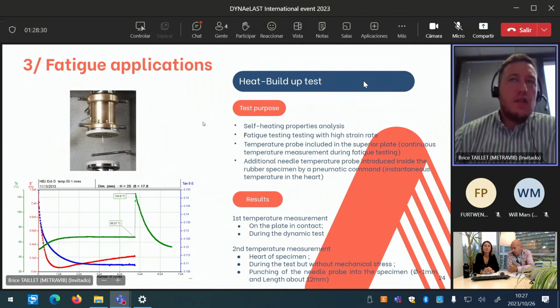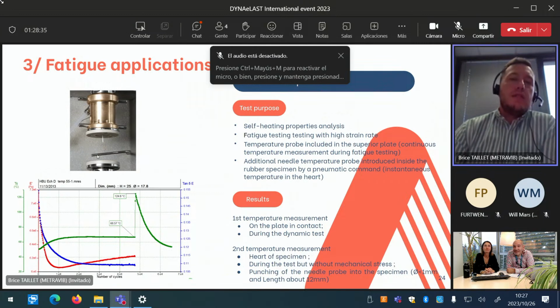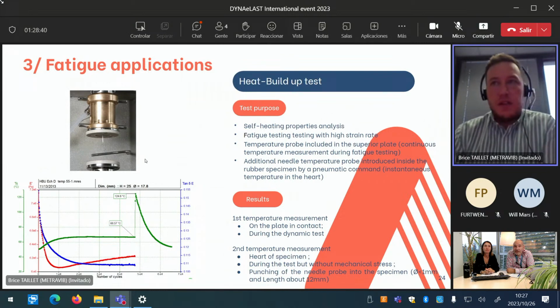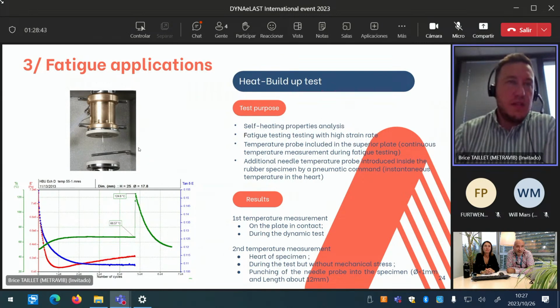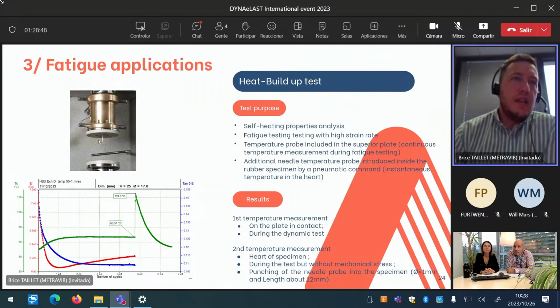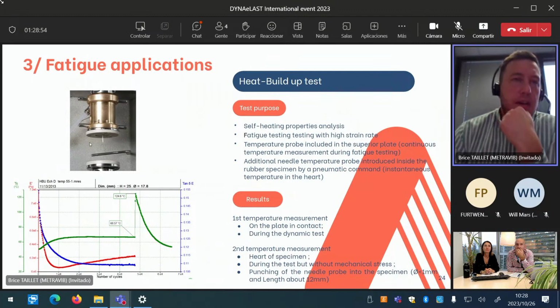Okay, one other interesting test is the heat buildup test. Heat buildup is to characterize the self-heating properties of materials. We use for this fatigue testing with high strain rate. We use a specific specimen holder in order to get the temperature just on contact on the plate on the rubber specimen, and we apply a fatigue test, and after the fatigue test we inject a needle inside the specimen in compression to get the internal temperature.